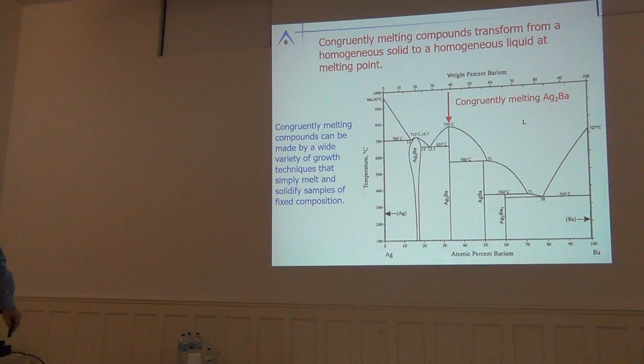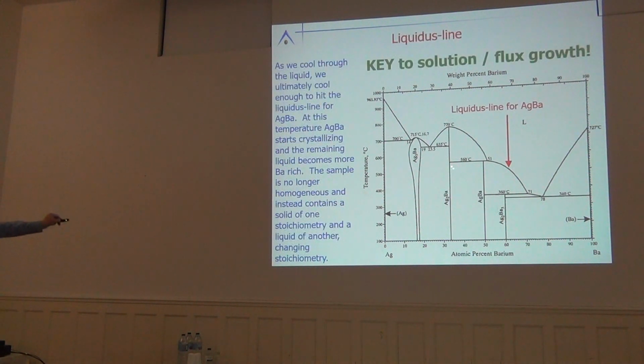Okay? Now, on the other hand, we have this line that separates our single phase liquid from our multi-phase, in many cases, regions. This is called the liquidus line. Okay? Now, this is important, and we'll come back to it again later. This is the key to crystal growth, okay? But for right now, we can see if we cool down at this composition, we have a single phase liquid until we hit this line, and then this line defines the composition of the existing liquid as I cool down, as I'm starting to grow silver barium. This defines the difference between a single phase region and a two phase region. Here I have a liquid of this composition and a solid of this composition. Okay? So we'll come back to this in greater detail in a moment.